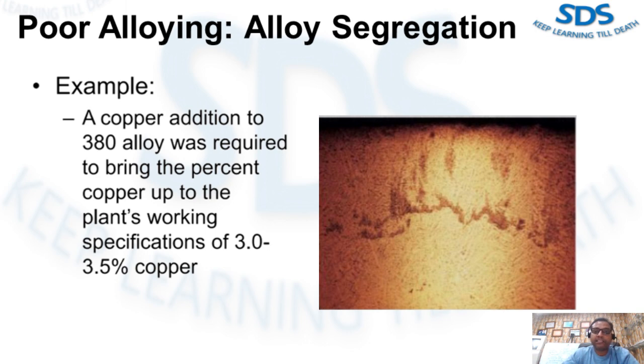Copper as well as zinc can segregate towards the bottom of the furnace when first added. When the furnace is tapped, a higher concentration might run out through the tap hole into the first ladle. It is best to add alloying elements in the form of master alloy — for example, 80% aluminum / 20% copper, or 80% aluminum / 20% silicon, or 90% aluminum / 5% Fe, etc. If available, the binary aluminum-copper alloy of 33% copper / 67% aluminum would be the easiest way to add copper units.